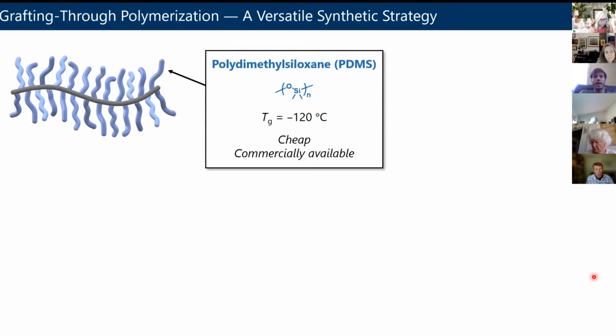Now, it may sound complicated, but I promise you it's not. Undergraduates in the lab do this on a regular basis. The reactions are very fast. They take of order 1 hour from start to finish. Then you can isolate the polymer. The polymers we'll start with today, again, are like that commercially available product Sylgard 184. They're made of polydimethylsiloxane, which has a repeat unit of Si and O, and the silicon has 2 carbons on it. And this is the polymer we'll build up as the side chains, where again, this gray backbone constitutes our polynorbornene that's created from the Grubbs catalyst.